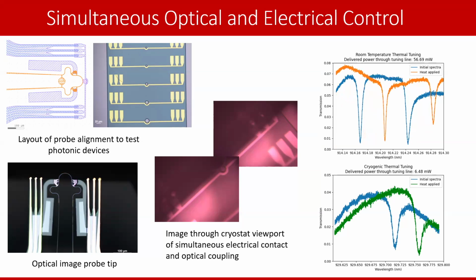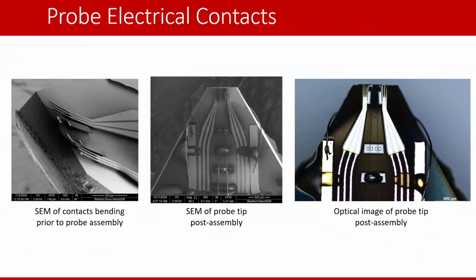That's what you see here, is that by very carefully aligning these extended electrodes off the tip of the probe, we're able to both optically and electrically control a number of devices. And this works at both ambient temperature and at cryogenics, although the thermal optic tuning of silicon carbide is less at cryogenics, so it required a bit more power. And this is what it looks like from above. You can see the waveguide here and the electrical line sticking down.